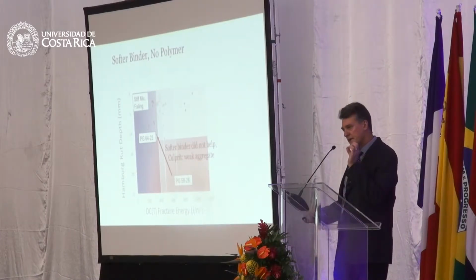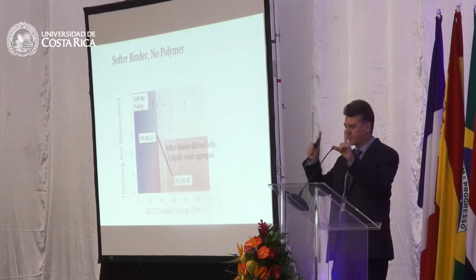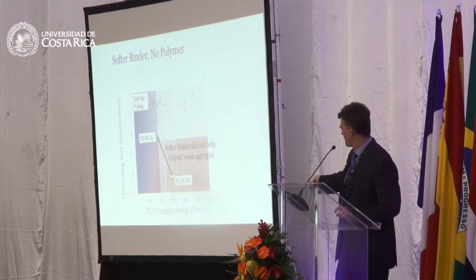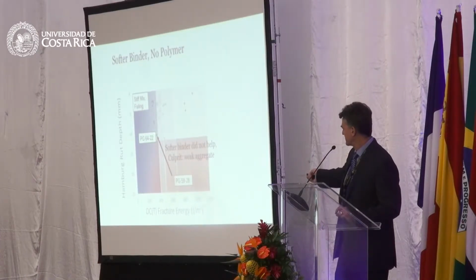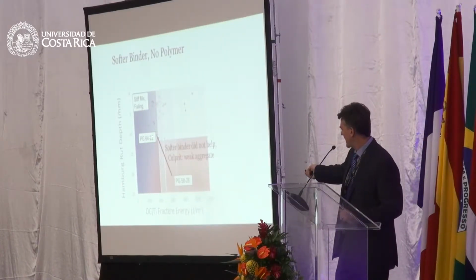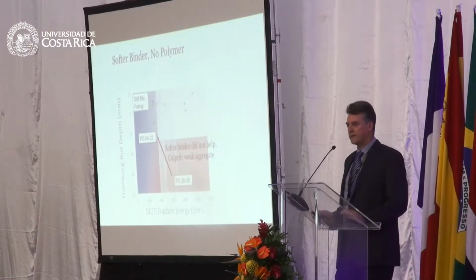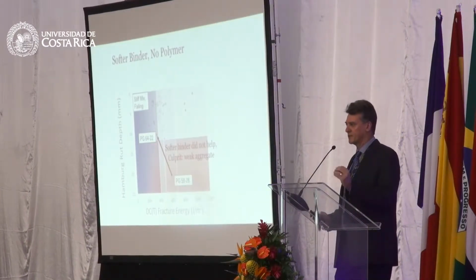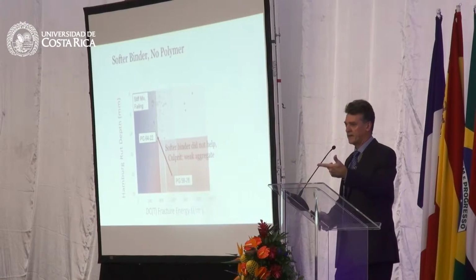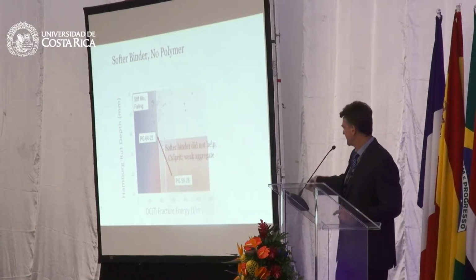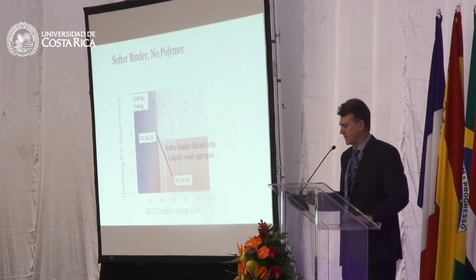But if you were to take a binder with a similar spread between the high and low temperature grade, it may not fix the mixture. You may just move into failure and cracking. So really, when you have a weak aggregate system, you're either going to have to improve that or use an improved binder, but just changing the viscosity characteristics of the binder doesn't necessarily save a mixture.